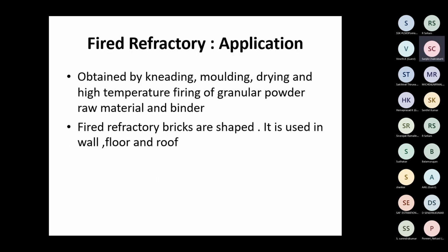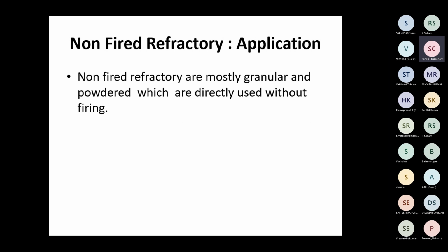Fired refractory is obtained by kneading, molding, drying, and high temperature firing of granular powder raw materials and binder. Fired refractory bricks are shaped. They are used in the wall, floor, and roof of a furnace. These are very shaped materials, with a particular size, as I already showed you. The standard size is there. There are non-standard bricks, but non-standard bricks are very costly. You cannot afford them for your furnaces. Non-fired refractories are mostly granular and powdered, and are directly used without firing.